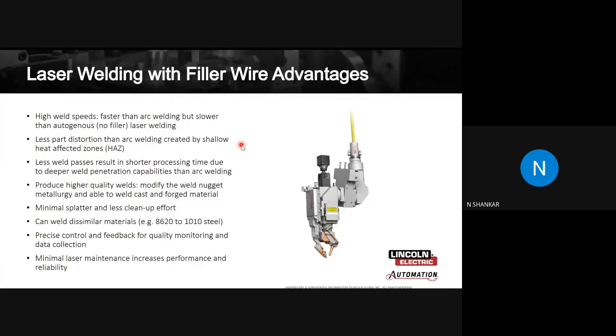It's faster than arc welding, but definitely slower than plain simple laser welding, or what you call autogenous laser welding. This is slower than autogenous laser welding, but this finds more specific applications where you can implement hybrid laser welding. But it's much faster than the conventional GMAW welding process. It gives you lesser part distortion than arc welding, because it gives you a much shallower heat affected zone, unlike the conventional arc welding machines. And it will give you much better, deeper, wider penetration than the GMAW process. It'll give you minimum spatter when compared to the GMAW process, so you don't have cleaning time, which is again an issue with the GMAW process.